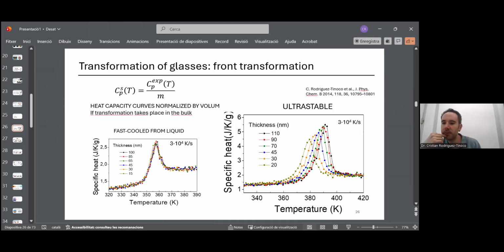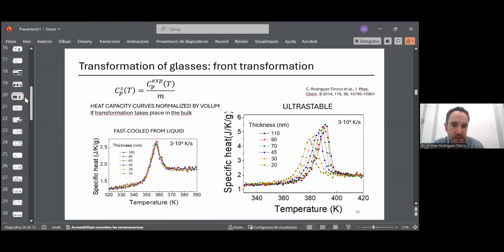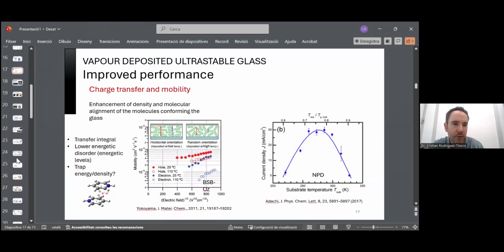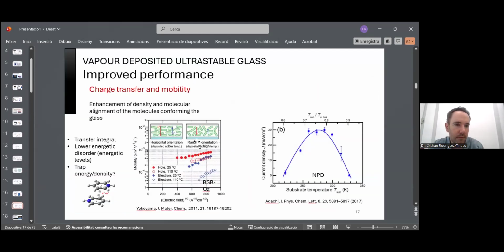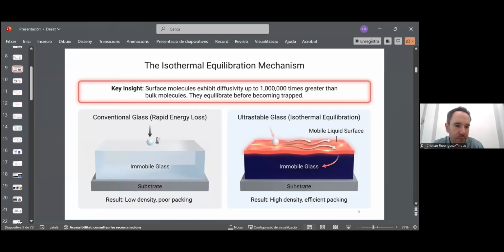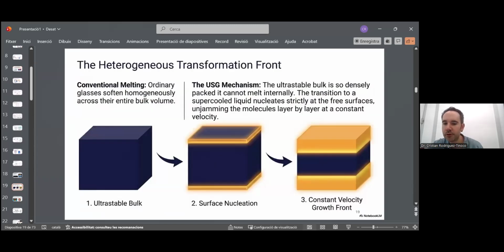But can you add some comments? What's the role of thickness? Why this shift we observed for ultrastable glasses? So you see, this ultrastable glass does not transform via bulk mechanism because the surface is free. We saw here in a previous slide. Let me look for this. It was here. So the glass transformed not from the bulk but from the surface.